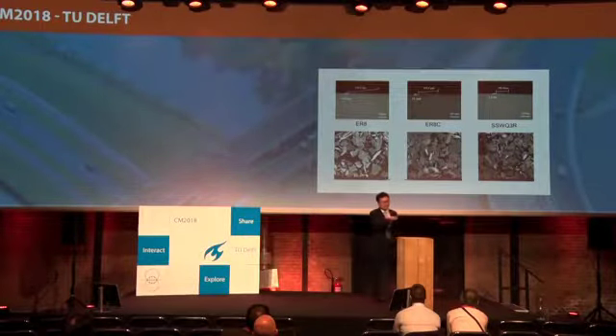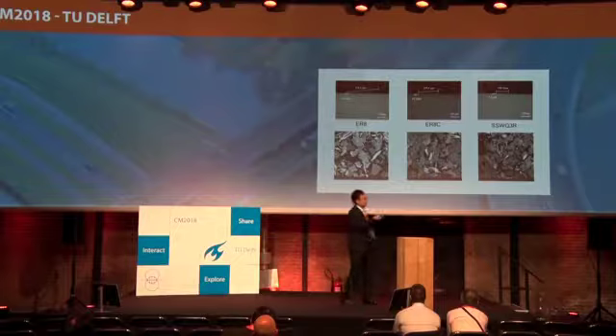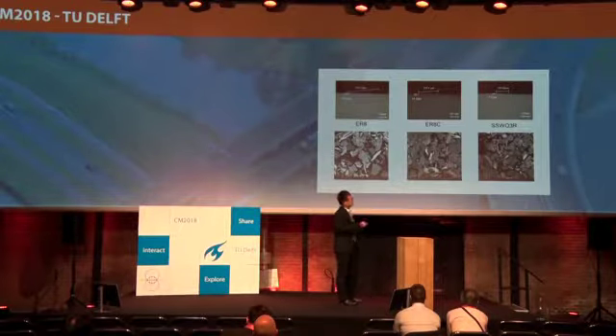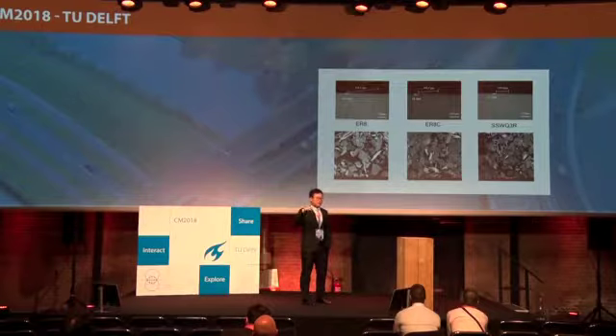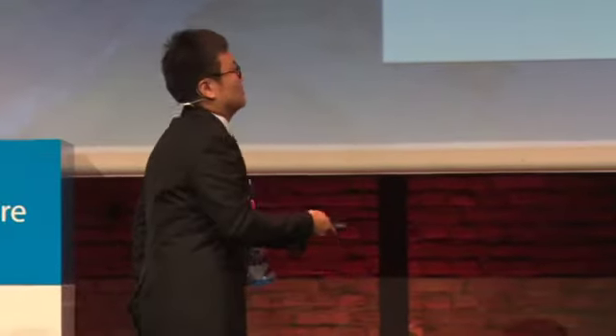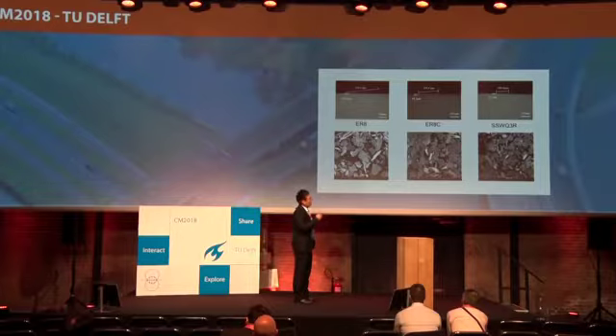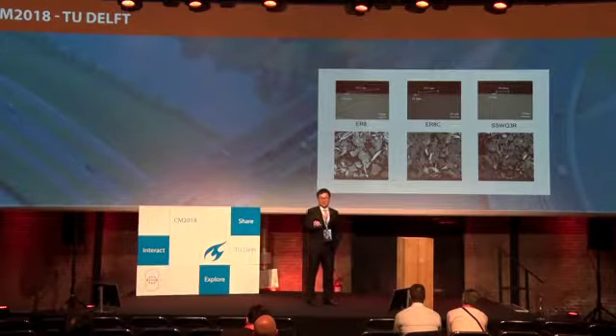And this is very interesting because it might also explain why the hard wheels have better resistance to RCF. Because the cracks initiate at the shallower layer of the material, and it will peel off the surface in smaller pieces. So the cracks won't go deep into the material, and thus the RCF will not propagate.